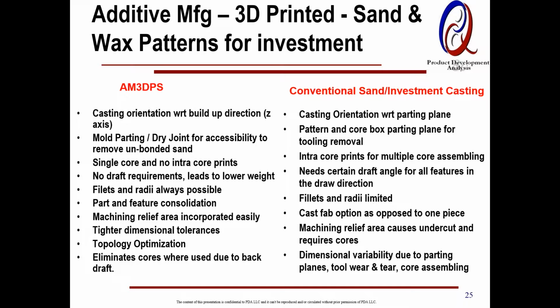Additive manufacturing, I'm sure most of you are quite familiar with. Our version of additive is strictly printing a mold without tooling, or printing a wax pattern without a wax die for investment casting, or printing a mold out of silica sand or zircon or chromite and you just pour the metal, which is quite different from additive manufacturing as understood. Metal additive is where you build layer by layer using metal powder and build the actual physical part. What we are doing here is making a cavity and pouring the same commercial alloy with the same ASTM spec, with the same known behavior, and the only magic is you don't use tooling.